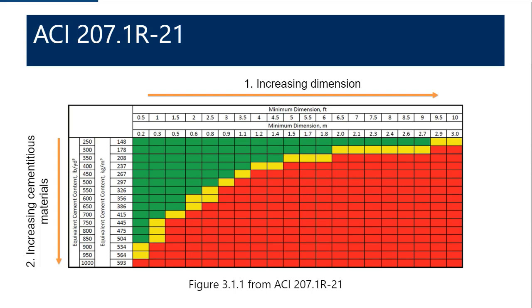So like I mentioned before, Class F fly ash only contributes about 50% of the heat as cement. And so its factor in this calculation of equivalent cement content is only about 0.5. And ACI gives guidance on how to calculate that for different SCMs. So yes, the total cementitious content does include fly ash, slag, and so on. But what I probably should have stated was really that it's the equivalent cement content that's governing a lot of the temperature rise in mass concrete. And that really depends on how much heat is released by those SCMs.